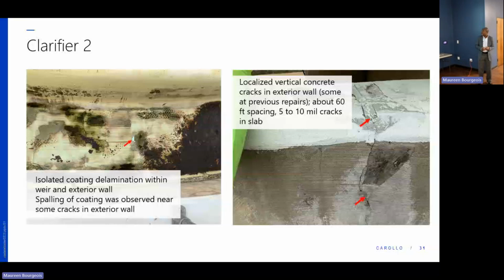So what did our non-destructive testing reveal for clarifier number 2? Well, the reinforcing is not actively corroding in the areas that we tested. All the handheld equipment testing data verifies that. The cover depths that it measured were 2.3 and 10.1. And in the walls, in these structures, we want at least a minimum of 2 inches. We do have that here, and so we are good there. We tested 10 cores in the lab under the additional lab testing to verify the compressive strength, which we talked about, which tells us the strength of the structure.